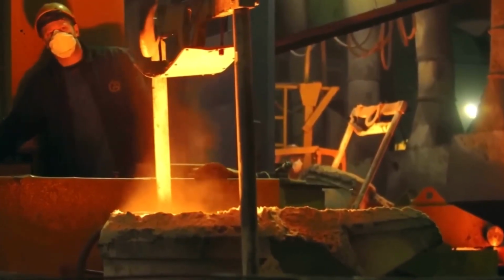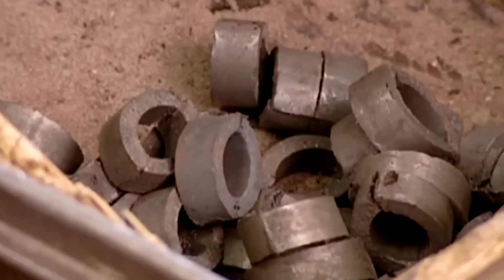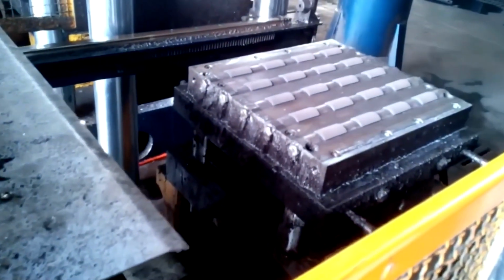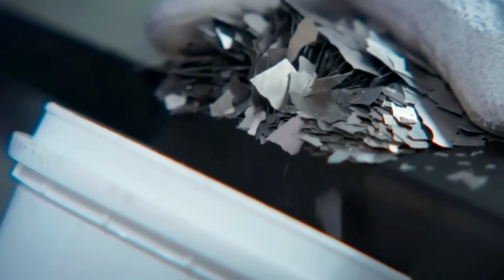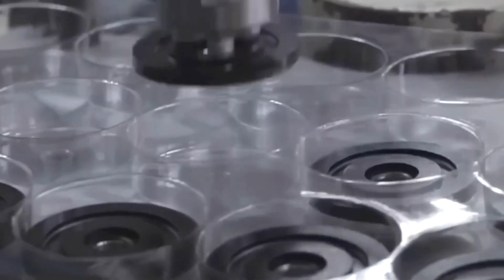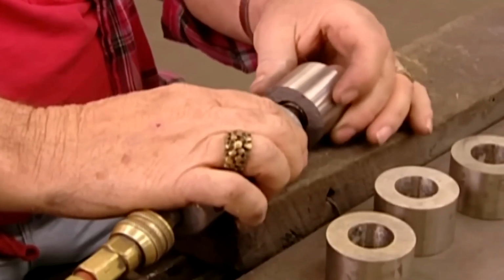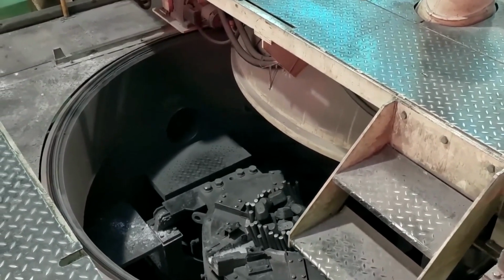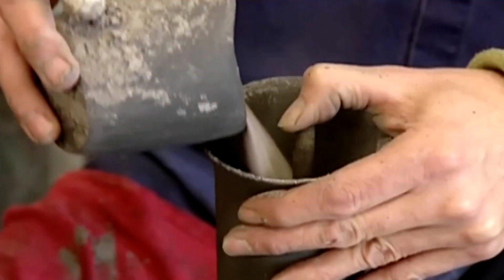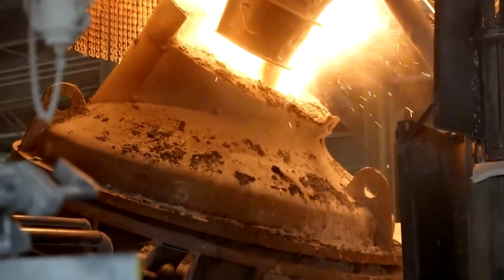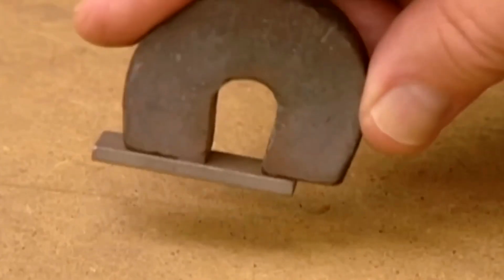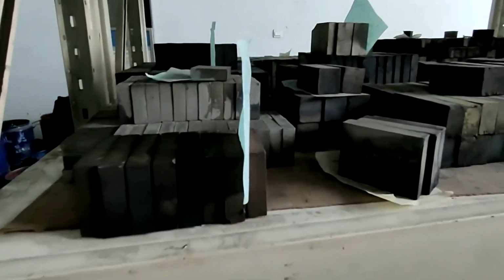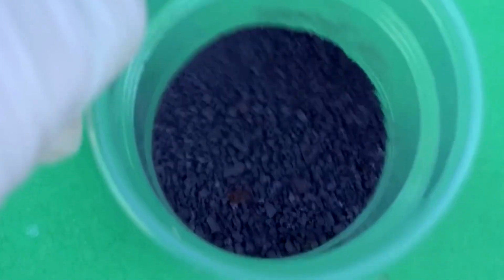Once the metals have completely liquefied, the molten alloy is subjected to a dramatic shock. It is poured onto a rapidly rotating drum, a technique that flash chills the liquid metal in a matter of seconds. This instantaneous cooling forces the alloy to solidify into thin, metallic flakes, each possessing a fine and uniform crystal structure. From here, the alloy is refined further, shattered into an ultra-fine powder within another inert gas environment to prevent any exposure to air. The resulting substance is a dark gray powder with a subtle violet hue, its individual particles measuring only a few microns across.